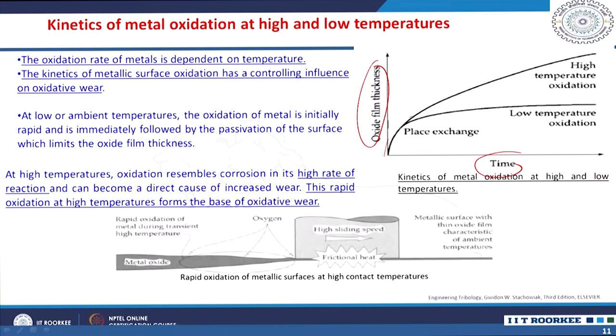Initially, there is low temperature oxidation and then the high temperature oxidation. At low or ambient temperatures, the oxidation of metal is initially rapid, followed by the passivation of the surface, which limits the oxide film thickness. You will have lesser film thickness in lower temperature oxidation. But at high temperature oxidation, oxidation resembles almost corrosion in its high rate of reaction and then becomes a direct cause of increased wear. So, you can have an oxide film thickness also increasing to a larger extent. This rapid oxidation at high temperatures forms the basis for the oxidative wear.